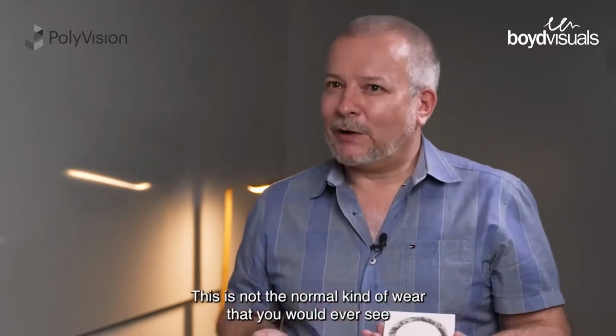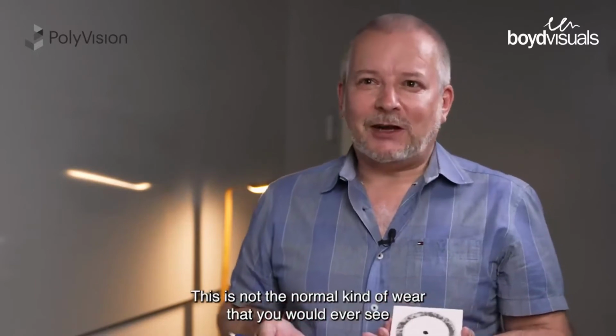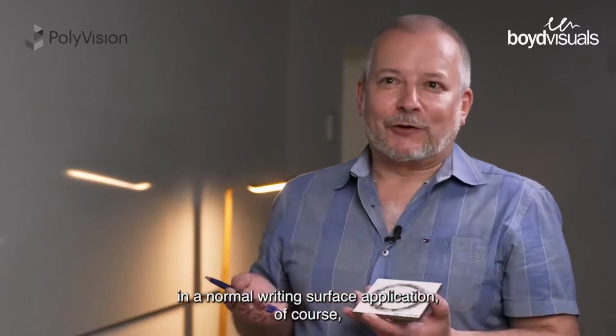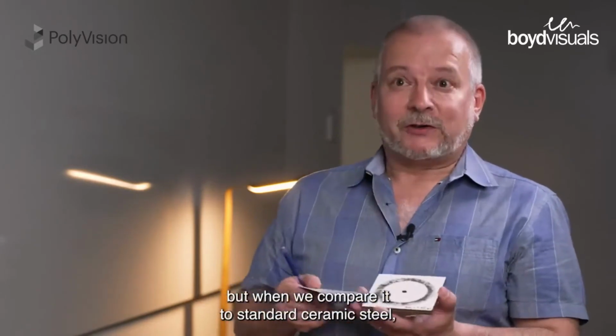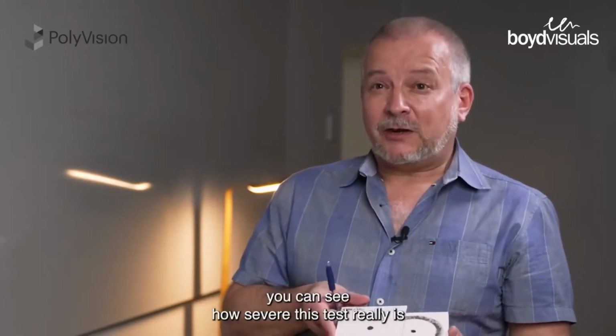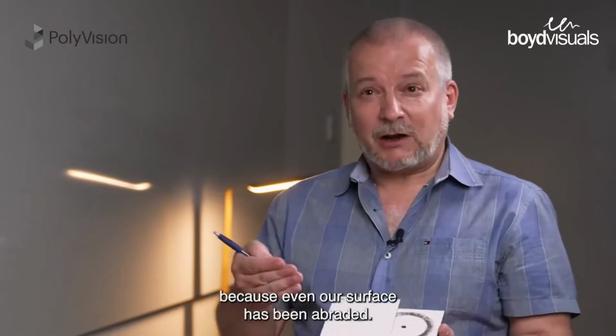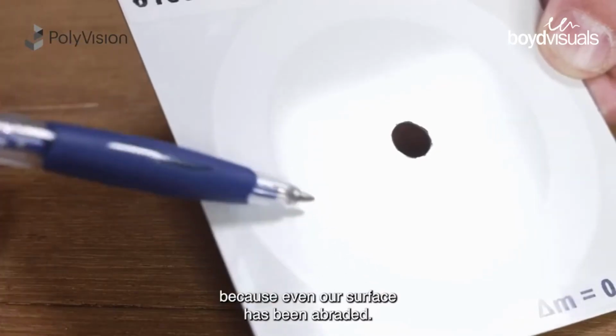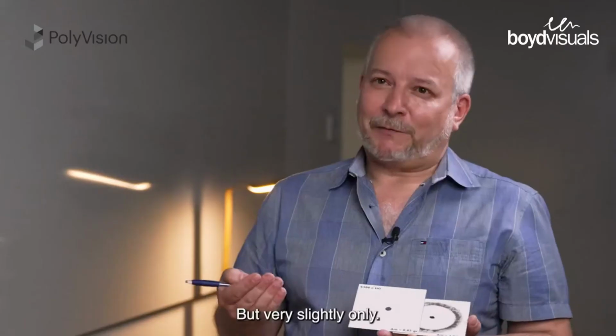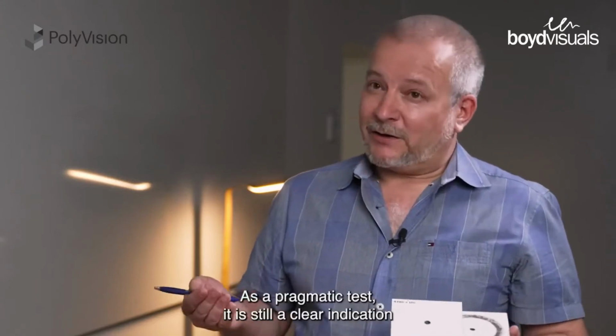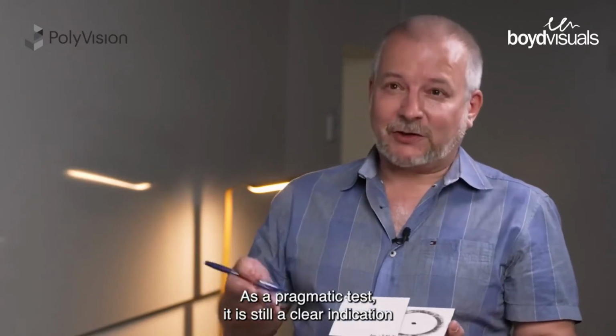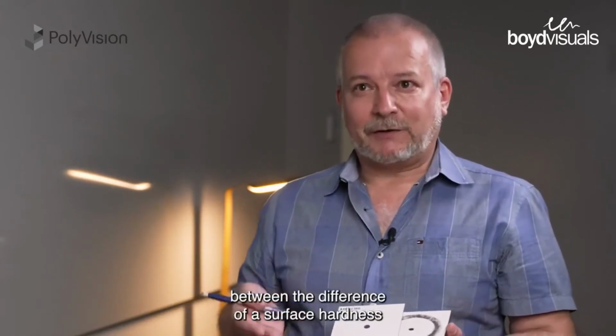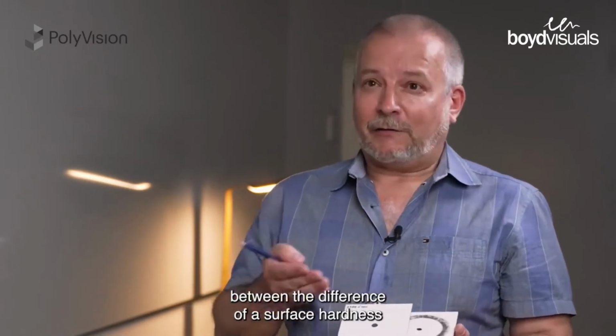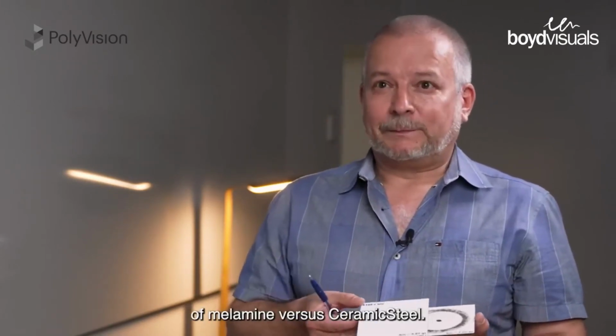This is not the normal kind of wear that you would ever see in a normal writing surface application, of course. But when we compare it to standard ceramic steel, you can see how severe this test really is, because even our surface has been abraded, but very slightly only. As it's not really a pragmatic test, it is still a clear indication of the difference in surface hardness of melamine versus ceramic steel.